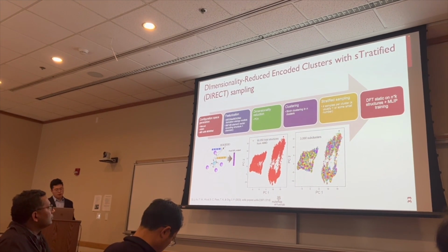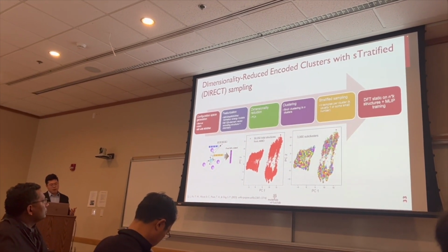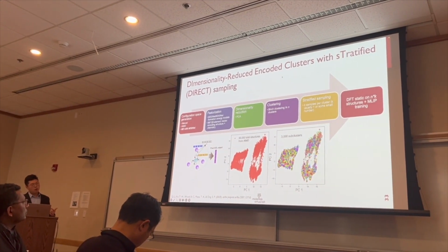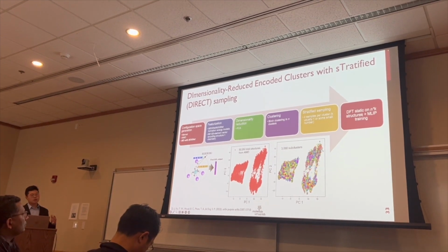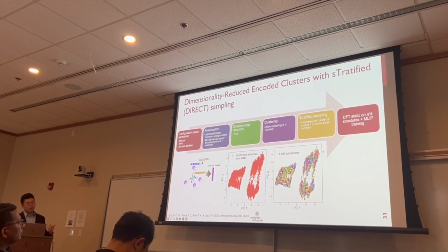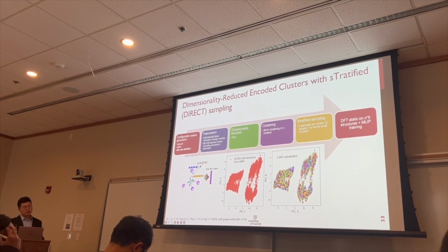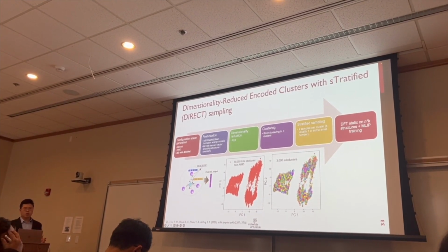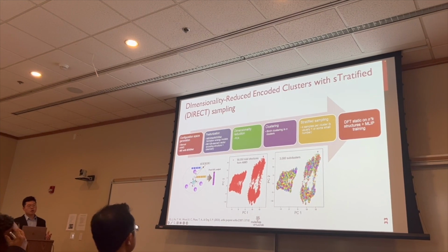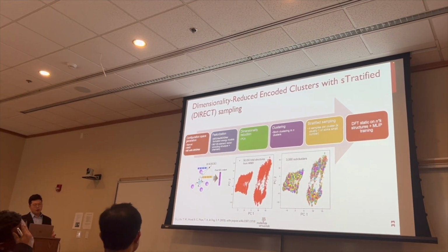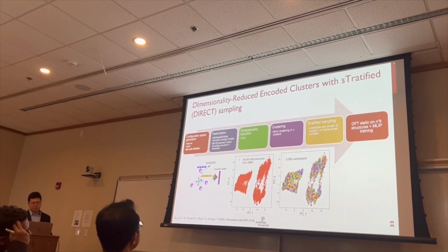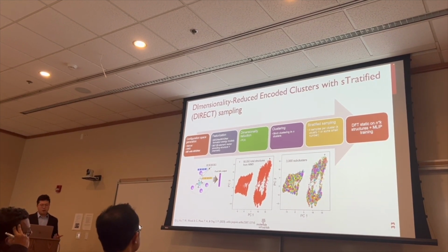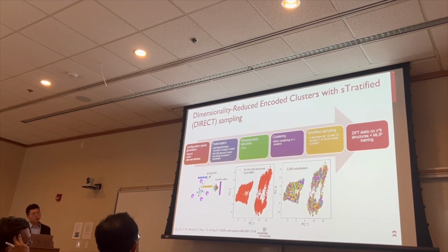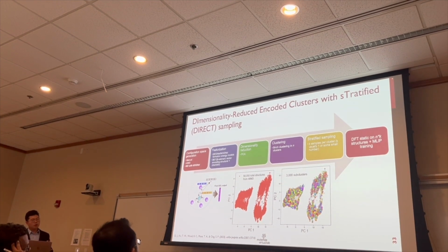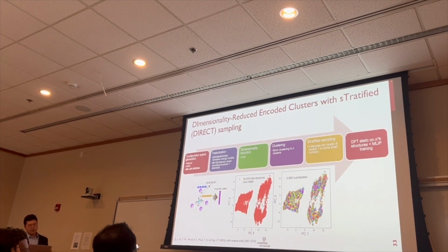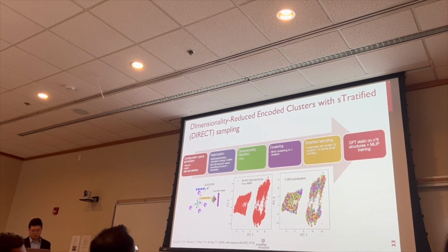In this way, we can actually cluster common structures into clusters and some very uncommon structures into those uncommon clusters. And following this step is the stratified sampling, where we treat those different clusters equally and sample the same number of structures from different clusters. So this way, you can imagine that we will select not only the common structures from the space, but also the very uncommon structures. And that's how we construct a hypothetically more robust or larger or more distinct dataset from this existing configuration space.